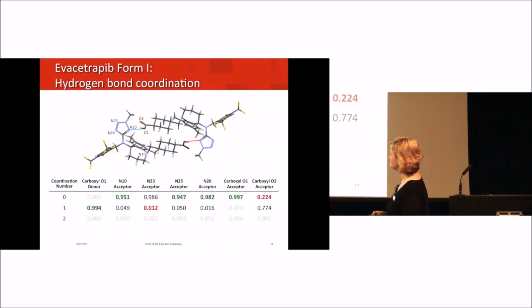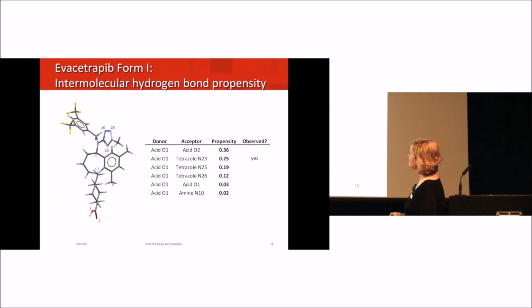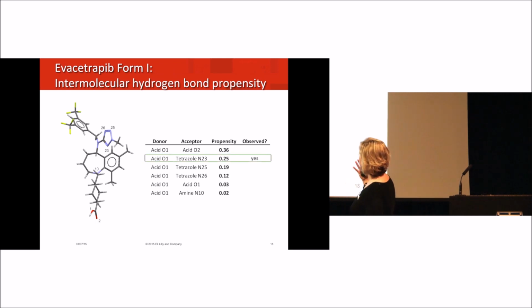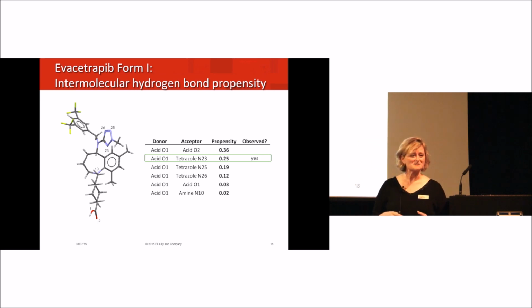So how about the form 1 structure? Now we see that our form 1 structure has no water in the picture, of course. And we see some instances of high hydrogen bond coordination, as well as some maybe not so satisfactory. I'm not so sure that this separates the monohydrate from form 1. Likewise, with the hydrogen bonding propensity, now we don't have the water in here, and you see that honestly there's a spread of propensities, and we're on the higher end of that, but it's not overwhelming. And the other thing I would point out is the model that I made is based on a statistical analysis of these functional groups, not all of which are terribly highly represented in the CSD. So the model's only so good as well. We have to recognize that.